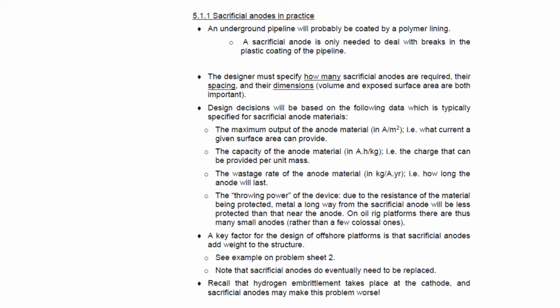This means that when we talked about hydrogen embrittlement as a corrosion mechanism, that can actually possibly be made worse by sacrificial anodes. It's more likely to be made worse by a powered system which applies a larger change in surface potential than is typically exerted by sacrificial anodes, but they can cause hydrogen embrittlement.